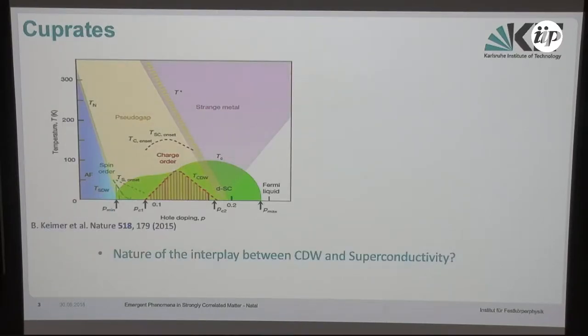So the phase diagram of high-temperature superconducting cuprates is known to most of you, I guess, and it was shown already a couple of times in this conference. You have the antiferromagnetic phase, you suppress antiferromagnetic order upon doping, and there's this superconducting dome that appears with a maximum Tc around 16%. What we discovered a few years back is that there was a charge ordered phase under the so-called pseudogap crossover or transition line T star, and this charge order we found to be strongly competing with superconductivity, and still the precise interplay and the nature of the interaction between superconductivity and charge order remains a bit mysterious.